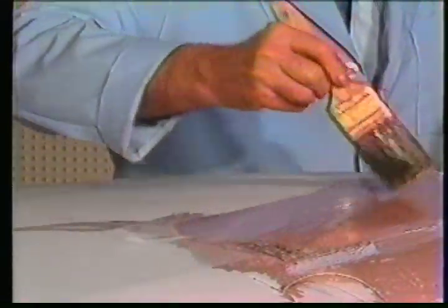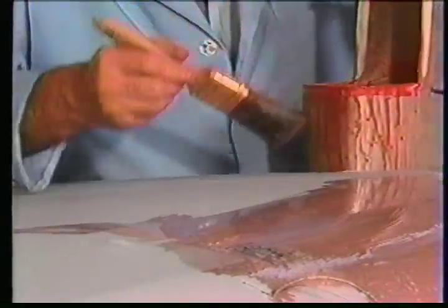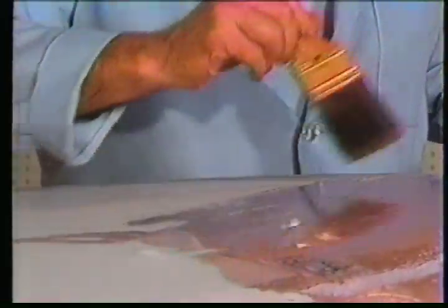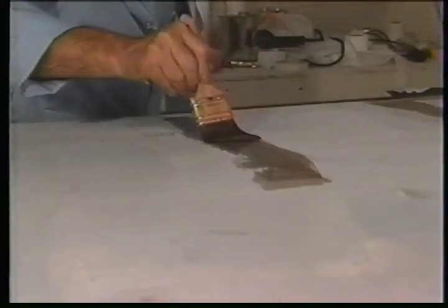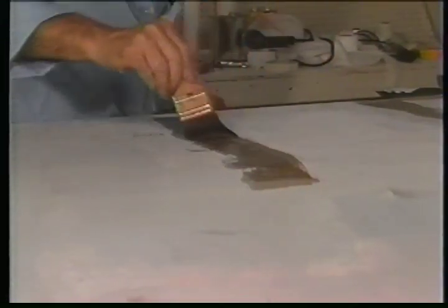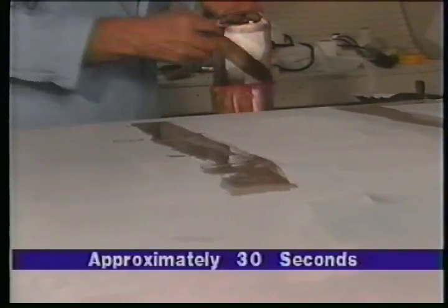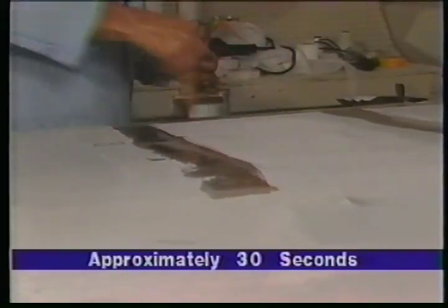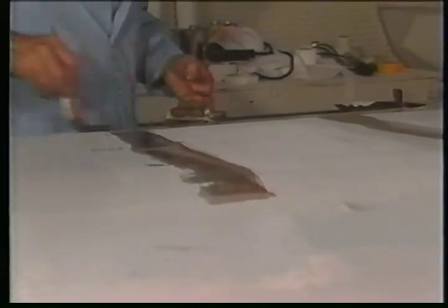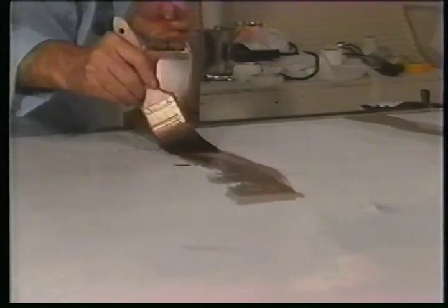Polybrush, thinned with equal parts of polyfiber reducer, is brushed through the fabric to soften the underlying precoats of polybrush, to embed and saturate the fabric to exclude all air. Work from one side across the surface to remove all bubbles. Where fabric tends to raise from lower areas of a plywood surface, a second pass with a brush approximately 30 seconds after first wetting the pre-coated surface will develop sufficient adhesion to hold the fabric down in the low areas if the depression is not too deep.